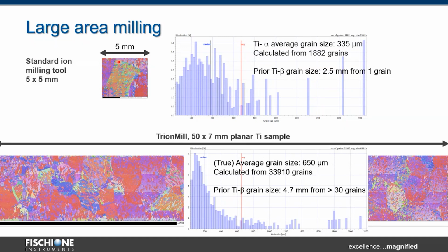And you can get true average grain size, which is 650 microns, almost two times bigger than evaluated from the 5 millimeters area. And of course, if you are interested in the alpha beta alpha transformation and prior beta grains, you can calculate their average size, and here it is calculated from over 30 grains as almost 5 millimeters, so almost 2 times bigger also. So as you can see here, you can get true grain size from large samples, and a small area will not give you this true answer and true characteristic of your material. Then you can mislead your interpretation and mis-evaluate the application of the material.